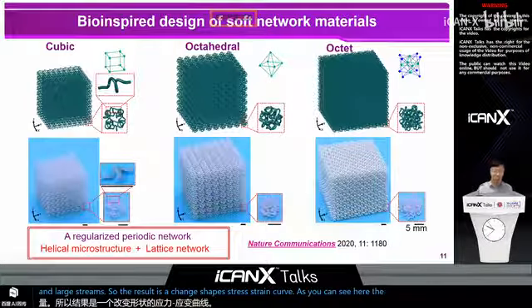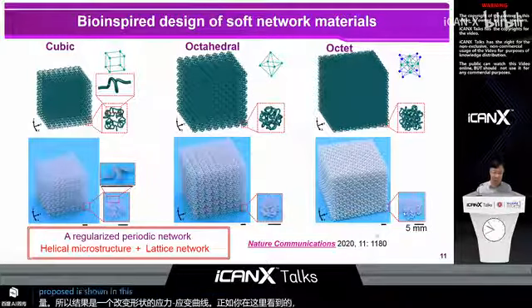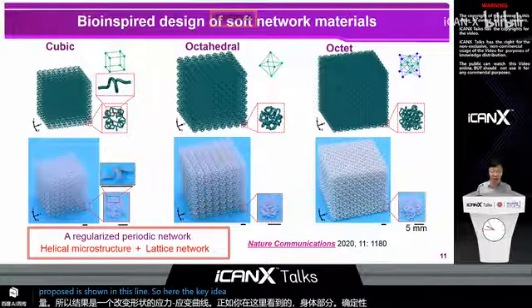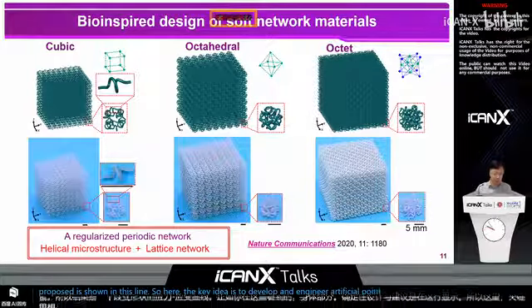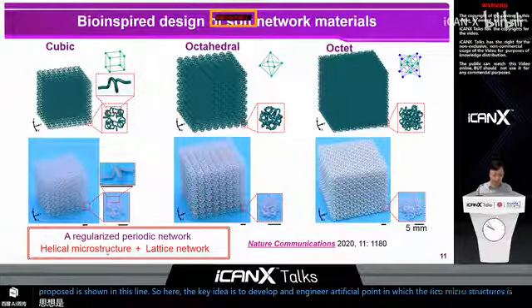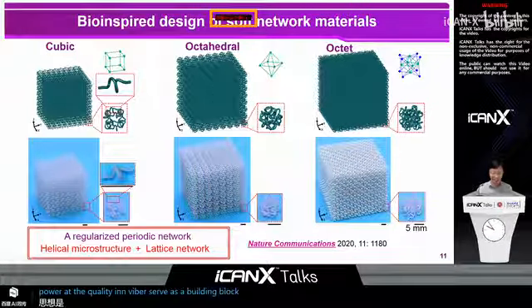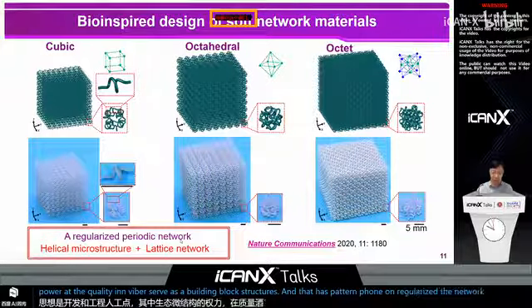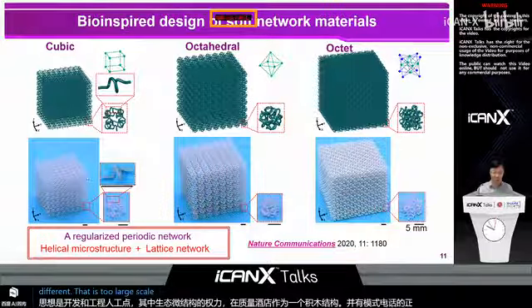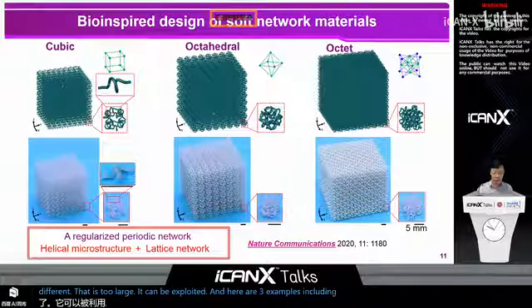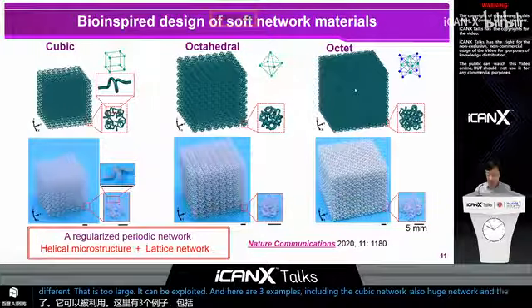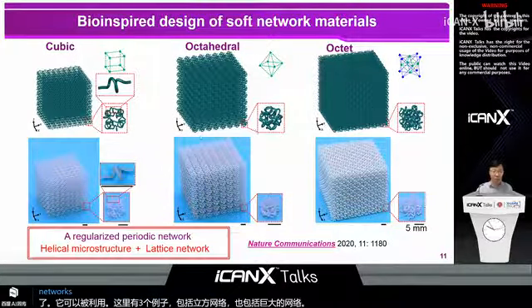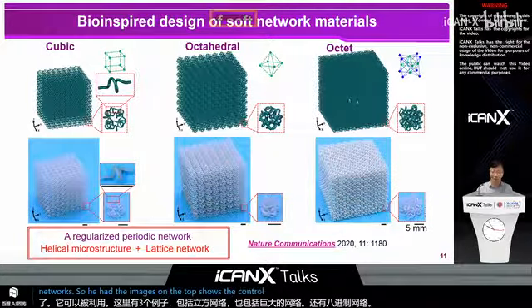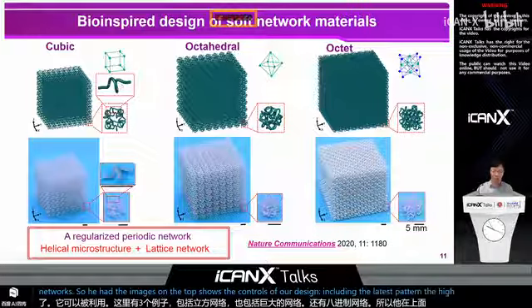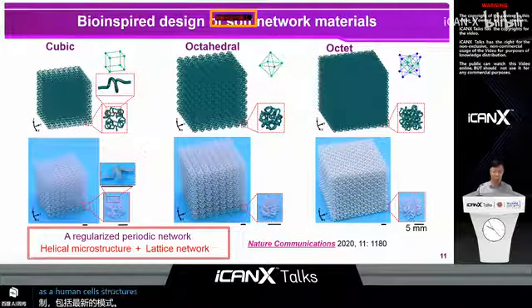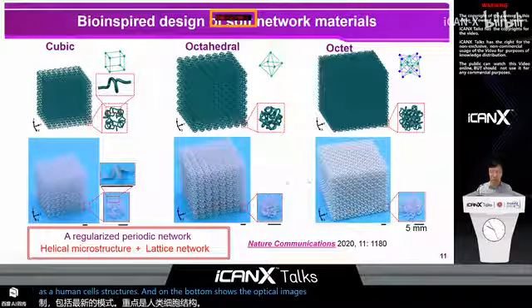The bio-inspired deterministic design we propose is shown in this slide. So here, the key idea is to develop an engineered artificial polymer in which the helical microstructures inspired by the collagen fiber serve as building block structures, and the lattice pattern forms a regularized network. Actually, different lattice topologies can be exploited, and here are 3 examples, including the cubic network, octahedral network, and the octet network. So here, the images on the top show the cartoons of our design, including the lattice pattern, the helical microstructures, and the unit-cell structures. And the bottom shows the optical images of our 3D printed samples.